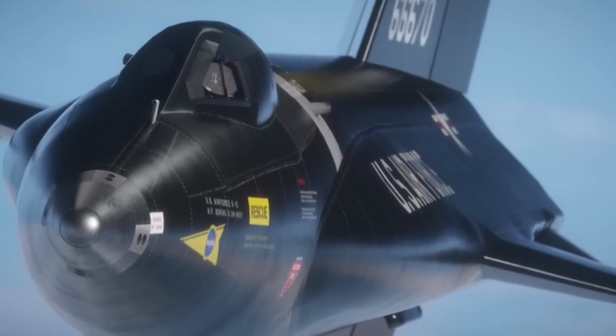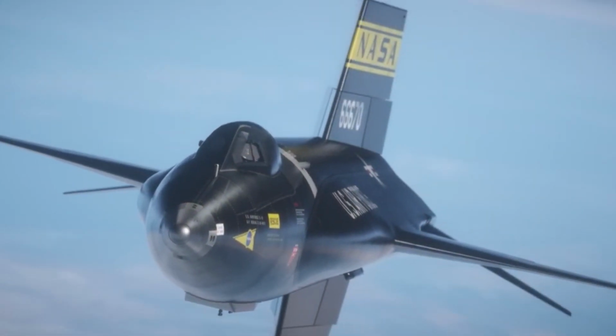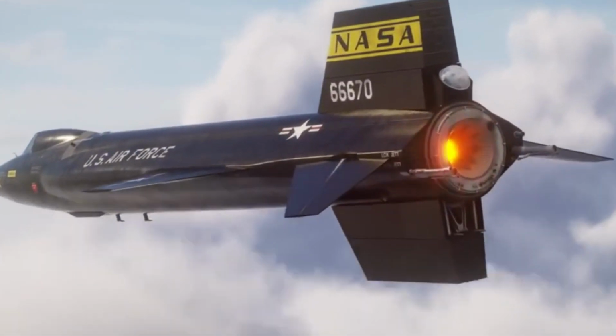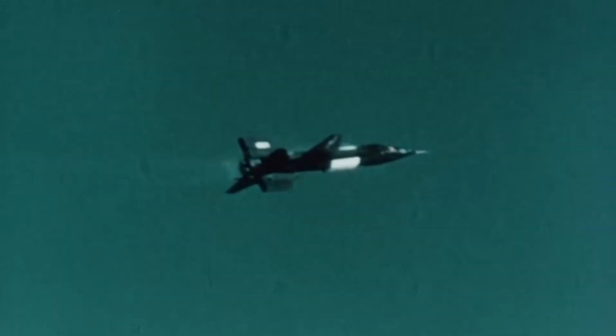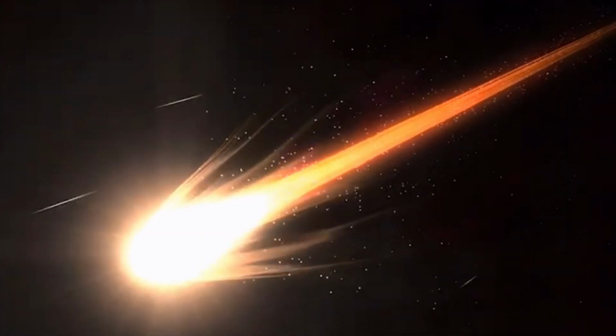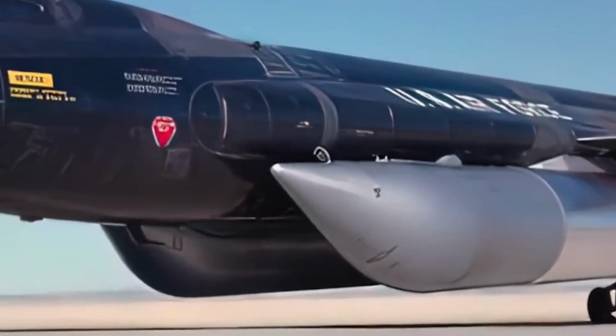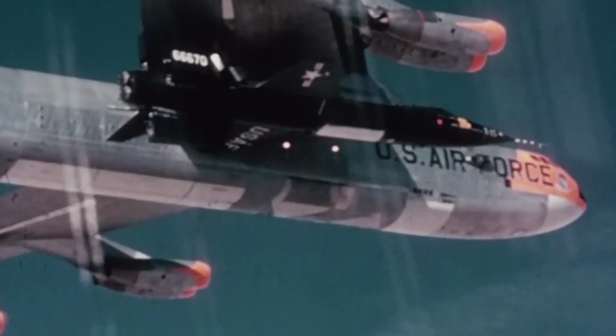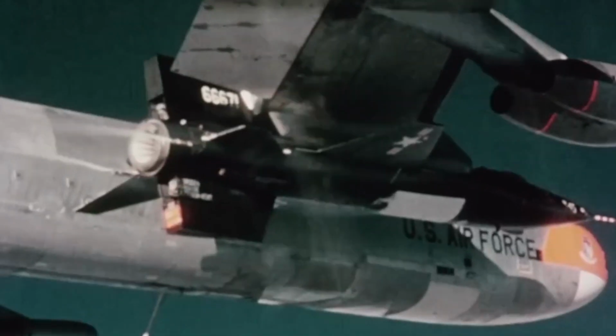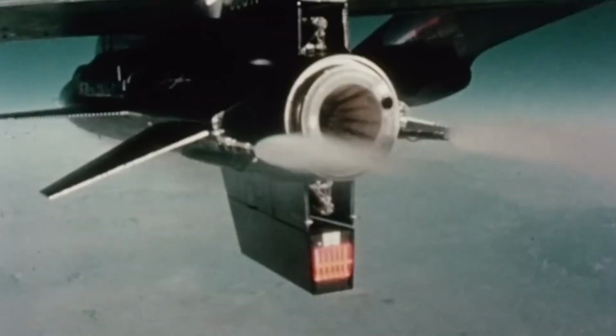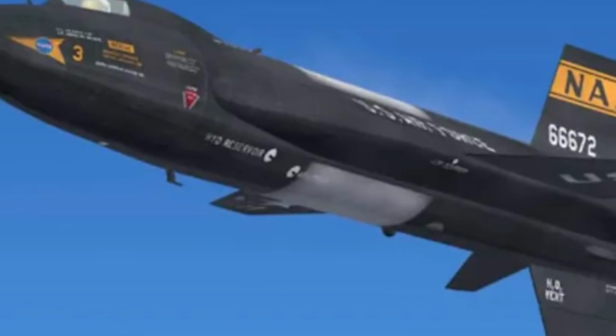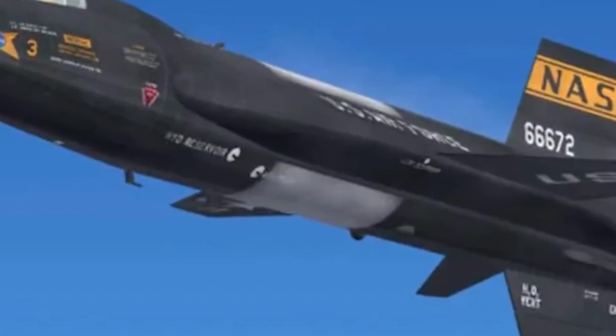of re-entry. On the space shuttle's third flight, the Kuiper Airborne Observatory flew underneath the orbiter as it re-entered and captured an infrared image of its searing hot belly, an experimental program to validate NASA's newly developed computational calculations and experimental testing. The nose and leading edges were a scorching 1,500 degrees Celsius, far beyond what the aluminum airframe underneath is capable of enduring. These leading edges, experiencing the hottest temperatures, needed the most heat-resistant material on the entire shuttle, a reinforced carbon-carbon composite. This amazing material was created in the years between the development of the X-15 and the